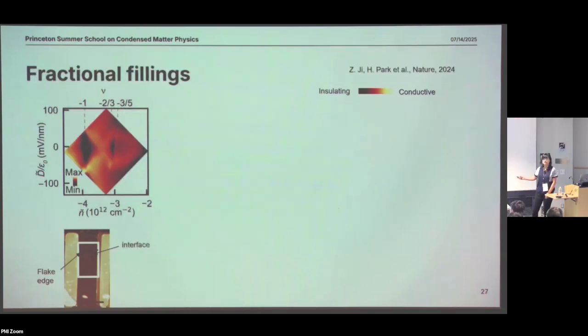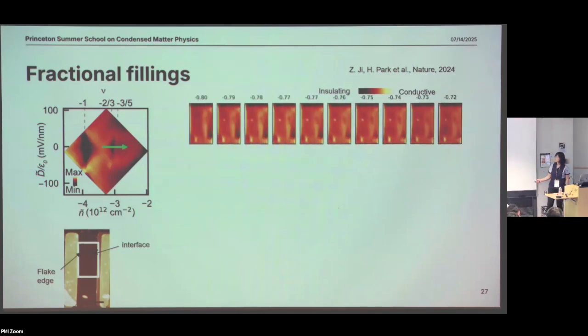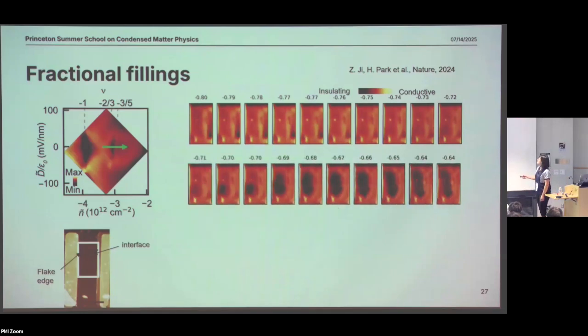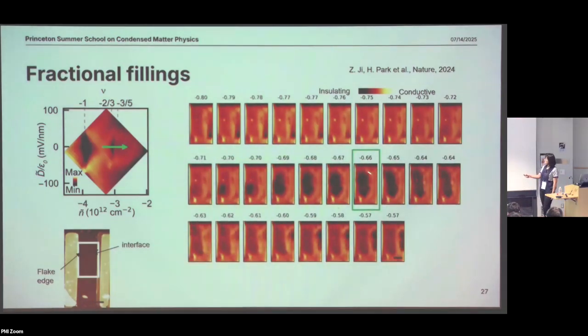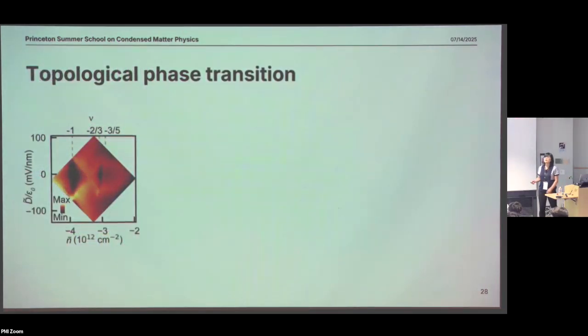Then we also went to the fractional fillings by changing the parameters in this parameter space following the green arrow that traverses -2/3 and -3/5. If we look at it again, it goes through -2/3 over here. Once again, from homogeneously bright, it becomes the edge being bright and the bulk being dark. Similarly, near nu equals -3/5, there's still this bulk-edge contrast. But what this contrast tells us has to be verified by driving a topological phase transition.